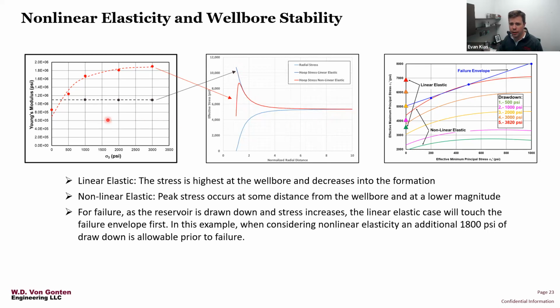But in the case of nonlinear elasticity, the peak stress actually occurs at some distance away from the wellbore surface, and in fact this results in a slightly lower stress in this case.